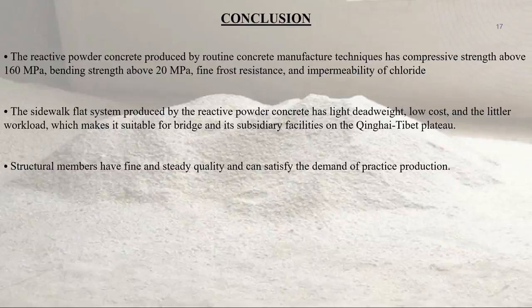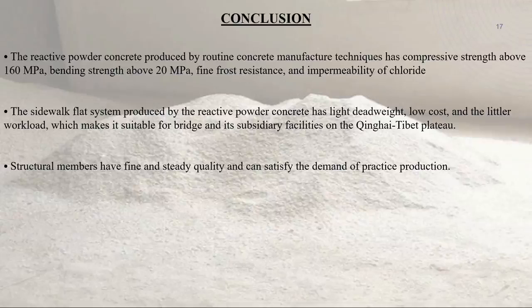Now coming to the conclusion. The reactive powder concrete produced by routine concrete manufacturing technique has compressive strength above 160 MPa and bending strength above 20 MPa, with fine frost resistance and impermeability to chloride. The sidewalk slab system produced by reactive powder concrete has light dead weight, low cost and little workload, making it suitable for bridges and subsidiary facilities on the Qinghai-Tibet plateau. Structural members have fine and steady quality and can satisfy the demands of practical production.